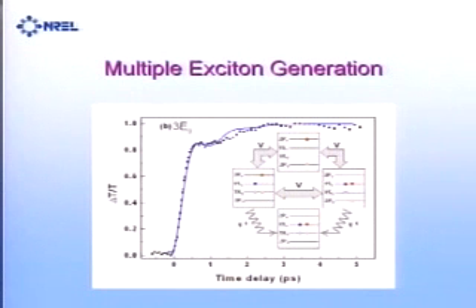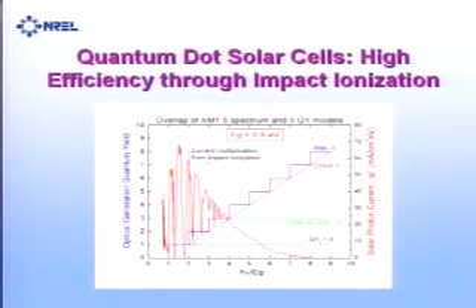So during this oscillation, this state, I don't show the 3 electrons, but the state that has 2 bi-exciton will undergo the dephasing, and you wind up with 2. It's possible to also generate 3, which you need to go to 4 times the band gap. I didn't show it. It gets complicated because you have many more states that can be superimposed. We've just begun to look at what effect this will have in a cell.